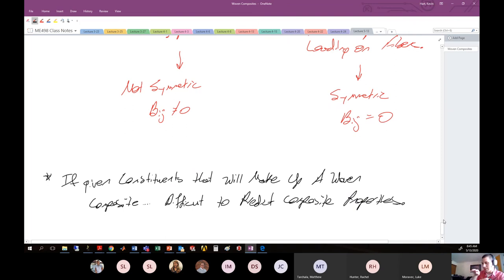So if I tell you, all right, I've got glass fibers running in this direction and Kevlar fibers running in this direction, the glass fibers have this mechanical performance, the Kevlar has this mechanical performance, then I infuse it with this resin. Estimate what the elastic modulus will be in the one direction and the two direction. Okay, it's actually really difficult to do, okay? Because you have interactions in the one direction with the glass fiber, but then there are Kevlar fibers across that direction. And then here you have Kevlar fibers in this direction and glass fibers across that direction. Okay, so you've got really complicated loading going on, and these fibers are interlocked with each other.